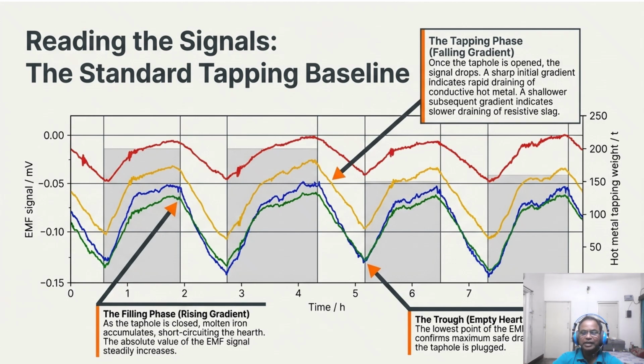During the filling phase, the signal gradient rises as molten iron accumulates and shorts out the hearth. Once the taphole is opened, the signal drops. A sharp gradient indicates a rapid iron drainage, while a shallower gradient indicates the slower flow of the resistive slag. The trough of the wave confirms the hearth is truly empty before you plug the taphole.